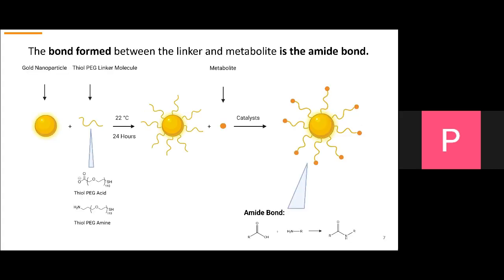To bind these metabolites to the surface of our nanoparticles, we use linker molecules composed of polyethylene glycol, which is shortened to PEG. With gold nanoparticles, we initially bind this linker to its surface, which not only helps bind the metabolite, but also provides stability to the nanoparticles by restricting them from binding together and aggregating. Then, in order to bind the metabolite, it's necessary that we form an amide bond.